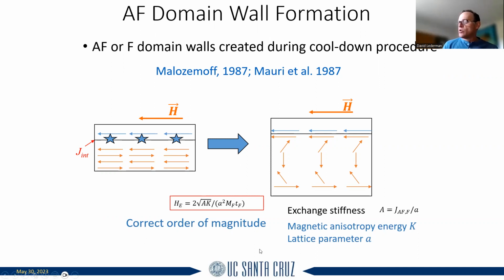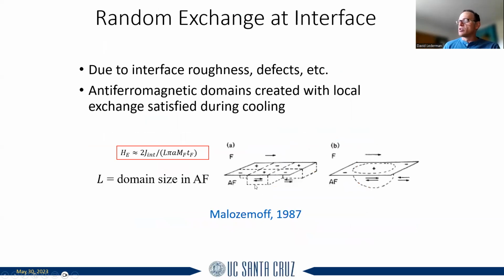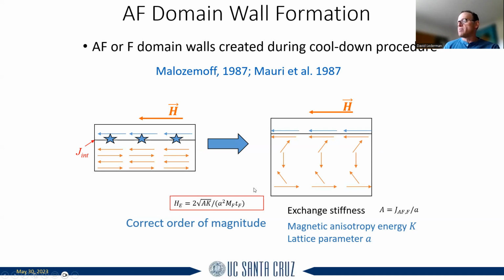releases its energy. And so the exchange bias, when you calculate it using this model, goes as the square root of A times K. A is like the interface exchange, basically the interface exchange divided by the lattice constant, and K again is the anisotropy. And this again gives you the correct order of magnitude. Of course, you still need some net exchange at the interface, and this doesn't deal with that, right? Whereas this model actually does. So maybe you need both, a combination of both models.